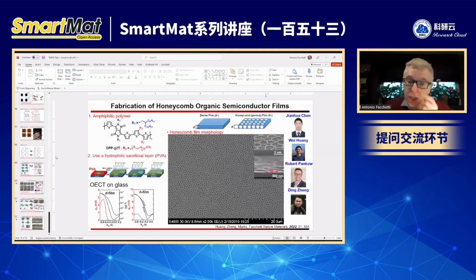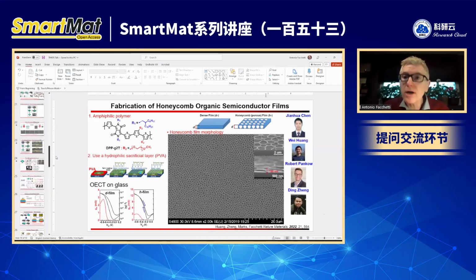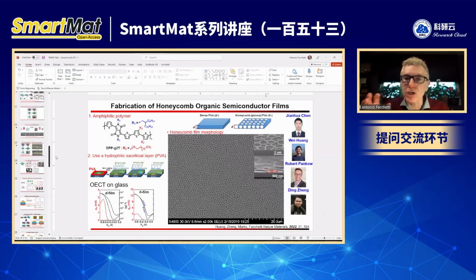We can control it by changing a little bit the concentration of the polymer, and a little bit changing the ratio. The solvent typically is a very volatile solvent. You need a very volatile solvent because you want, during spin coating, the solvent to evaporate fast, so you cool the substrate. You cool the substrate, water condenses, because you made the substrate cold. Solvent evaporates, it needs heat, it cools the substrate. So usually for this solution, you need chloroform, methanol, very high volatility solvents. So you can change the concentration, you can use a different ratio between methanol and chloroform.